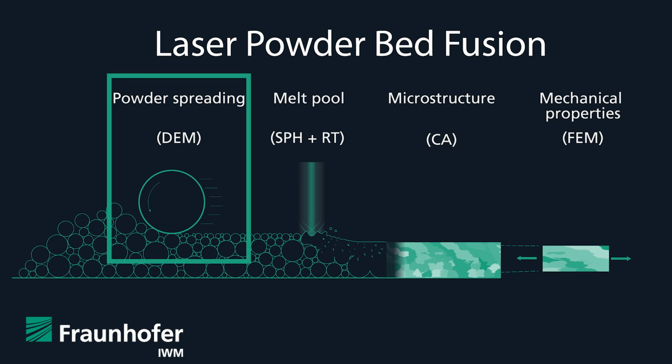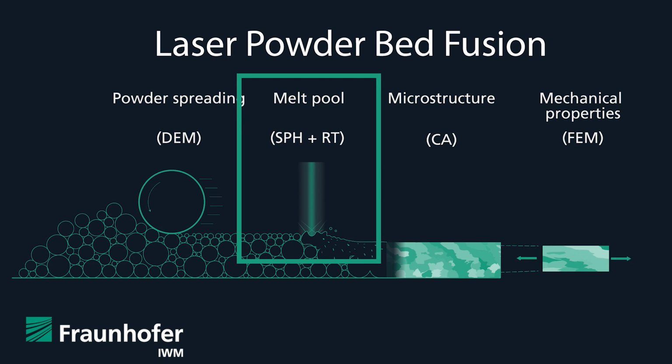The powder spreading is simulated using the Discrete Element Method that can model all types of powder flow behavior. The result of this simulation is the powder distribution in the build chamber. A ray tracing algorithm describes reflection and refraction of the laser beam.